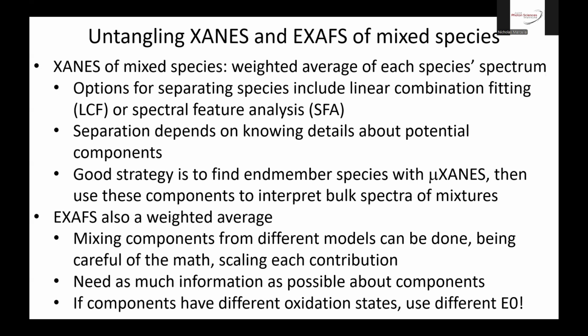XAFS is also a weighted average, and so when you do a full XAFS analysis, data processing, you can mix in components from different models into that fitting process, as long as you're careful with the math and keep track of scaling of each contribution. That's doable. It makes it complicated, but it needs as much information as possible on the components. The more you know about the sample, the better. Then you can tease these things apart. And the interesting thing that I ran into with sulfur is that if the components in an XAFS spectrum have different oxidation states, you need to use very different E0 values for those components in your fitting model. So it can get pretty complicated, but not impossible.